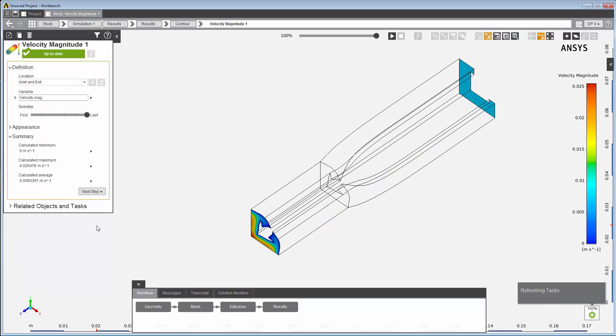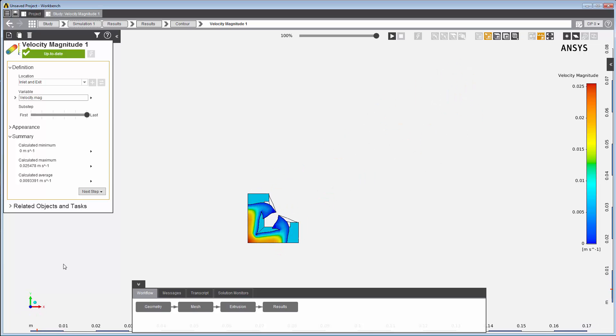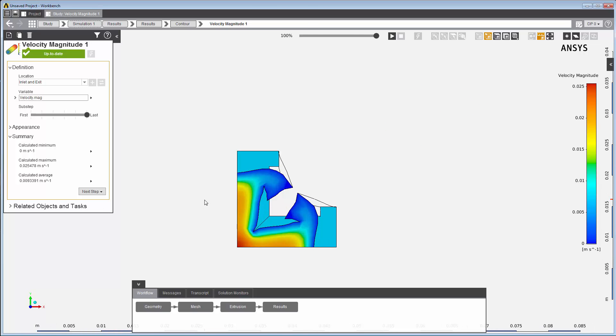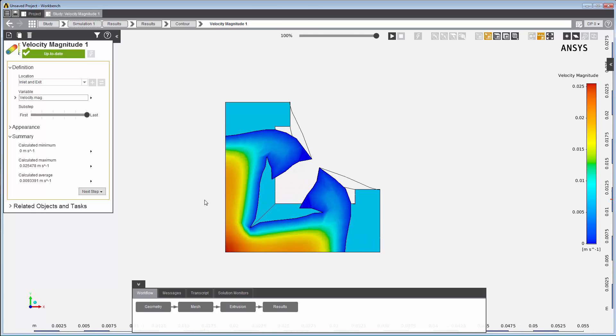The final cross section of the die is significantly different from the one of the extrudate, due to the velocity rearrangement that occurs at the die lip. Within the die, the velocity is higher at the center of the channel, while it must be constant in the extrudate where no force is applied. This redistribution of matter induces deformation.